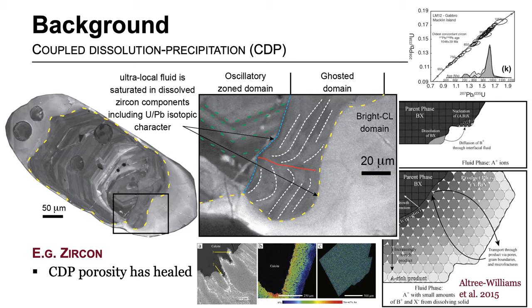We infer that this process creates complex age patterns, like is shown in the upper right. The colored diagrams at the bottom are there to remind me that with prolonged exposure to the fluid, the new recrystallized grain can homogenize its chemistry and it can heal the porosity, essentially covering its tracks, so it's hard to recognize that the process happened.